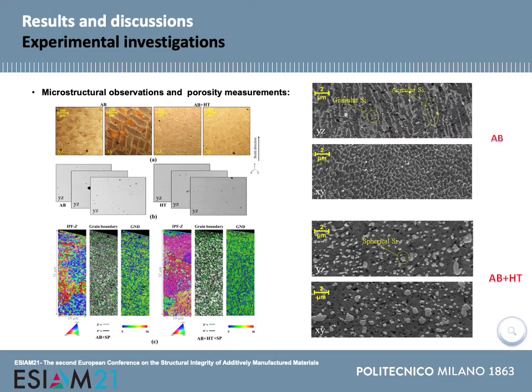Microstructure observation using optical microscopy, SEM and EBSD were performed in both longitudinal and transversal sections of both as-built and heat-treated material. In the as-built state, you can see the traces of laser and the hatchings visibly, and after heat treatment, it can be observed that most of the traces are becoming invisible, and the microstructures become more homogenized. In addition, in the as-built state, granular and acicular silicon in the shape of a network can be seen around the aluminum matrix, but after applying heat treatment, the silicon phase becomes a spherical shape.